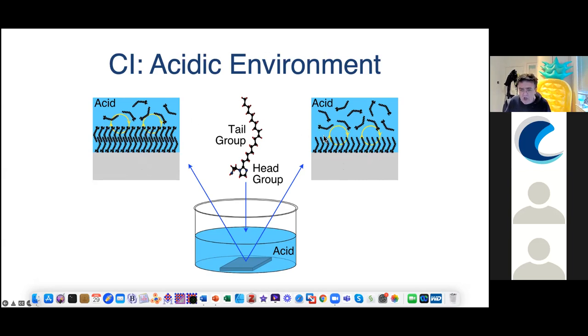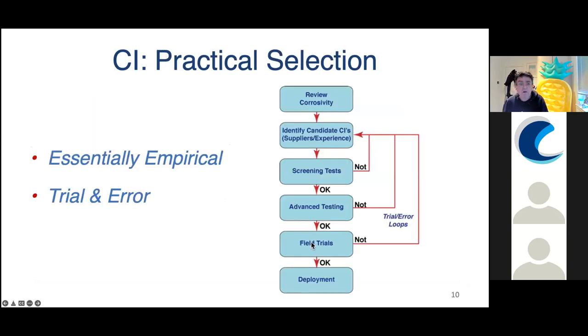And these yellow circles and arrows are there to indicate that the layer is dynamic. It's forming and reforming all the time. If you reduce the concentration of molecules in the solution, typically the concentration of the molecules at the surface will reduce quite rapidly. So you have to have this dynamic equilibrium between the bulk solution and the surface to get this inhibitor layer on, unless you have a large degree of persistency where molecules can last for a longer time on the surface.